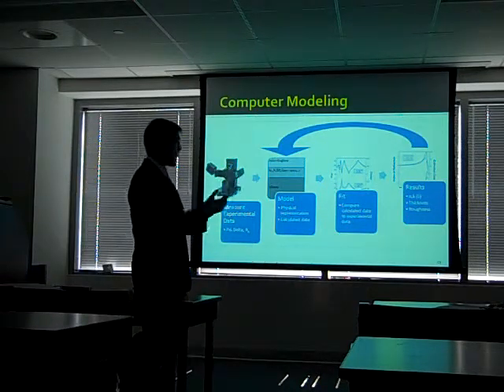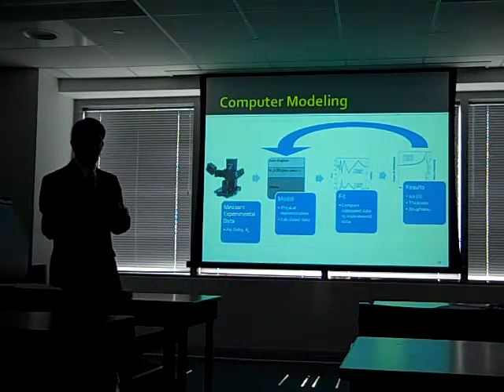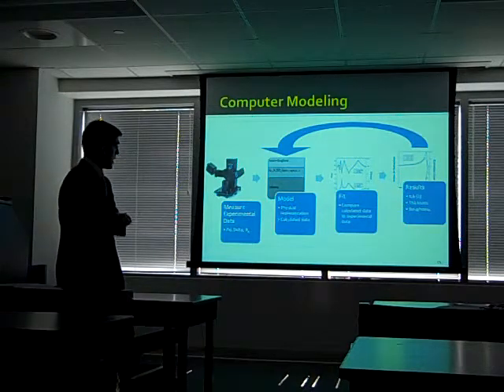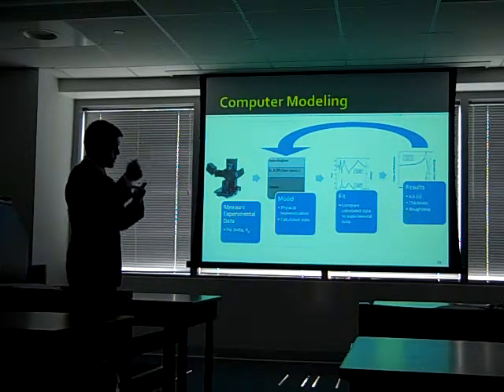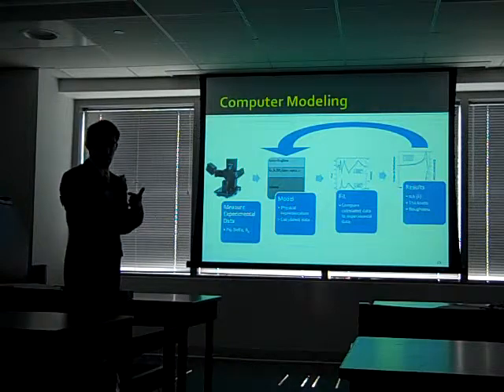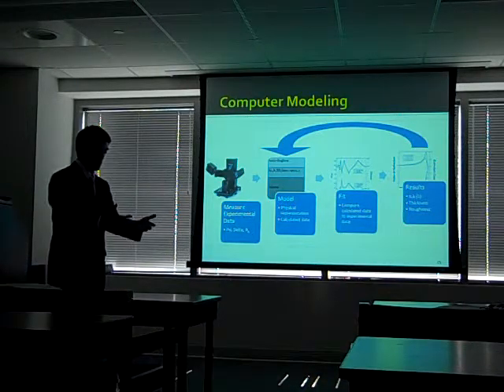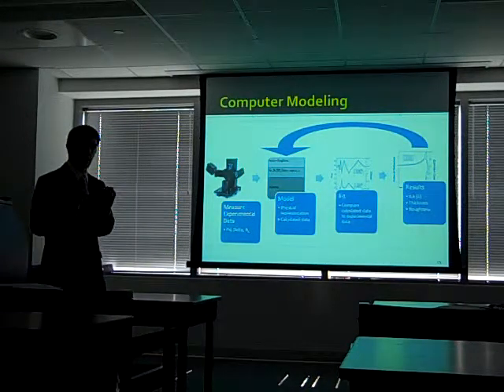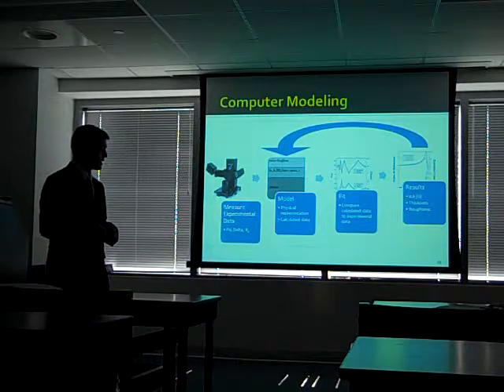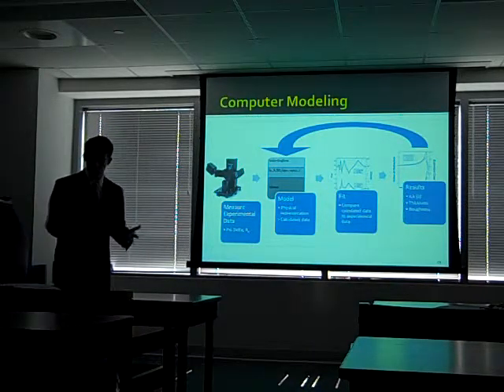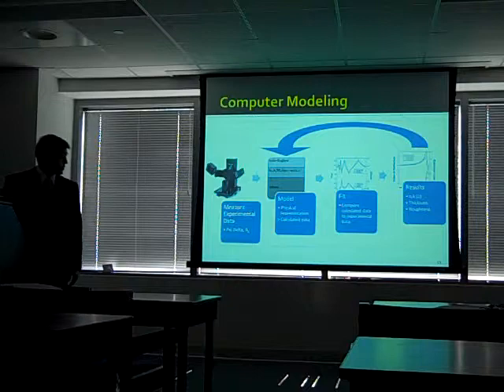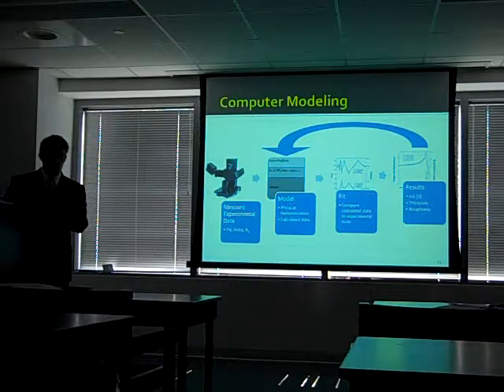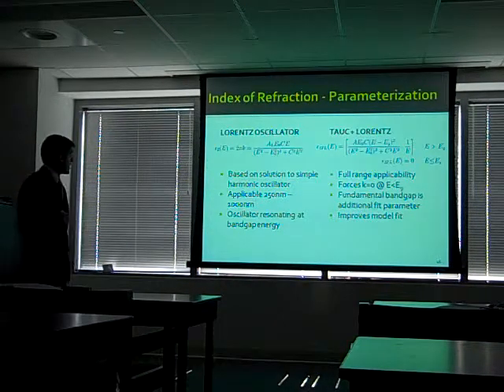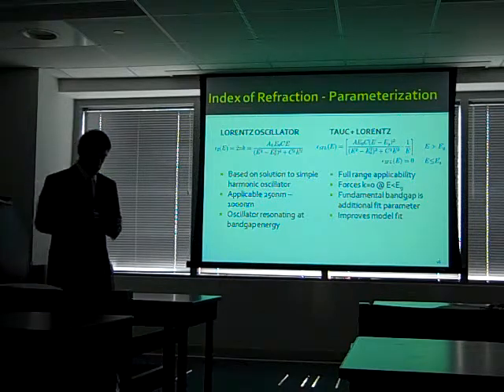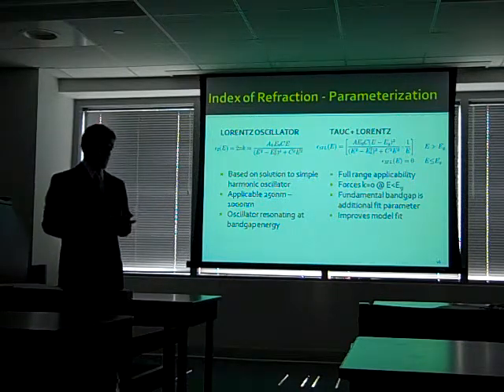So the result is an optimized thickness for the different layers and optimized optical constants. And you can use that result as a better initial guess for your model and iterate the process to continually reduce your mean squared error. Again, the mean squared error, or MSE, is a quantitative indication of the quality of your fit. A mean squared error of 0 would be a perfect fit. Okay. With computer modeling, the fewer variables you have, the better.